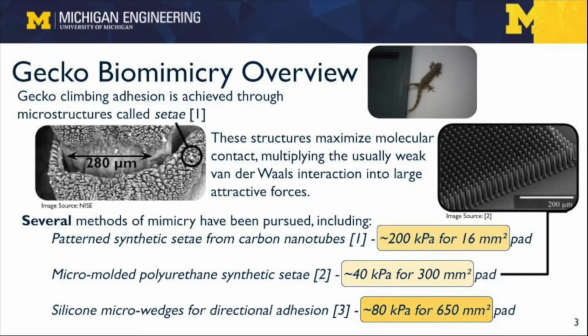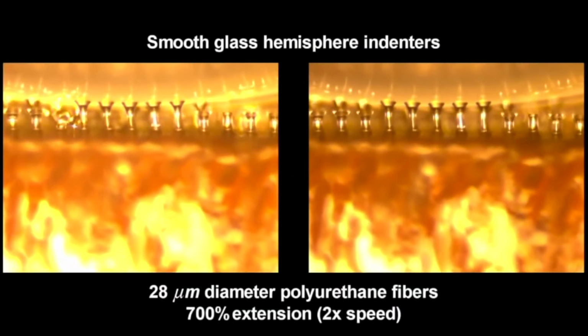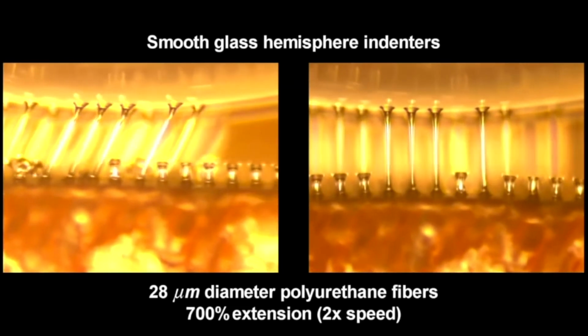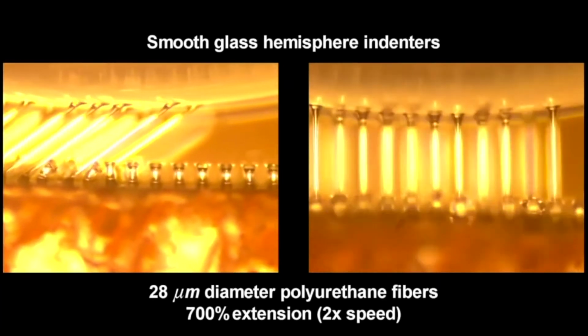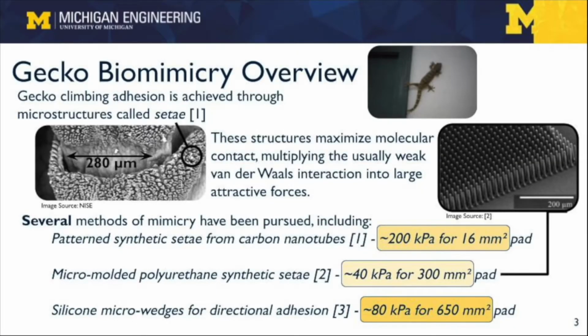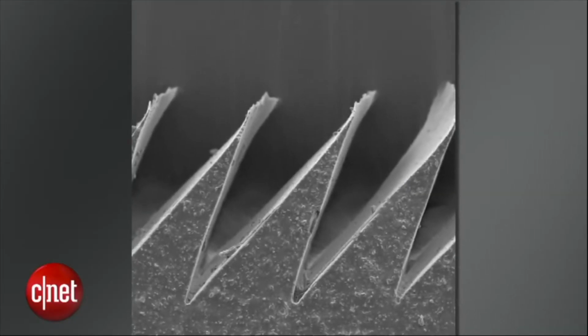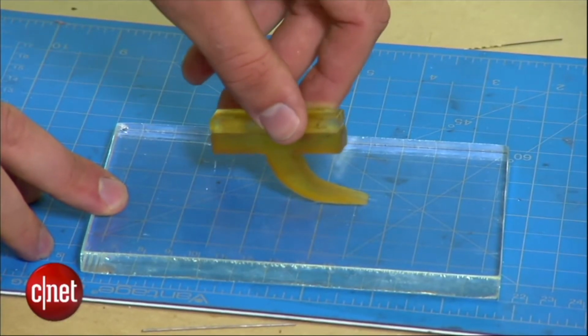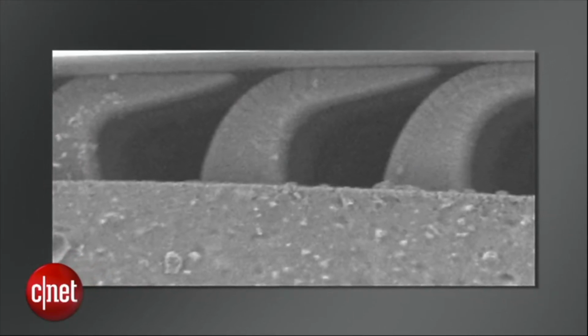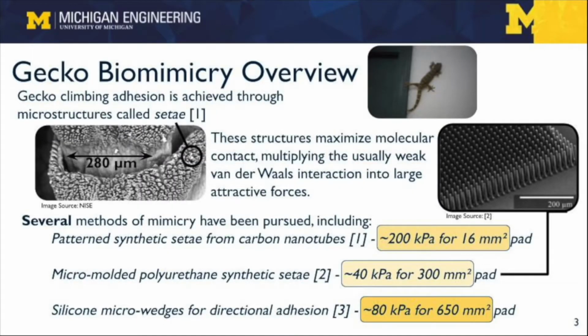This technology was able to create a 16 square millimeter adhesive pad that had a shear stress capacity of 200 kilopascals. Metin Sitti at Carnegie Mellon University developed polyurethane synthetic setae molded in microscopically detailed molds that were created with lithography, leading to a 300 square millimeter adhesive pad that had a shear stress capacity of 40 kilopascals. Mark Cutkosky at Stanford University developed silicone microwedges, which patterned a 650 square millimeter adhesive pad that had a shear stress capacity of 80 kilopascals.